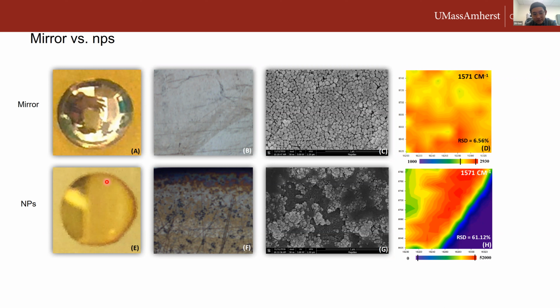So both gold and silver can be made into this mirror. In this case, we use the gold mirror. The gold mirror successfully detects the pesticide down to 1 ppm, and the signal is very uniform. Whereas with the other method, using the colloid solutions, you can see that the signal is scattered everywhere. And because the nanoparticles are scattered everywhere, we don't know where to look exactly. So in some cases, at such low concentrations, we sometimes fail to detect any useful signals.